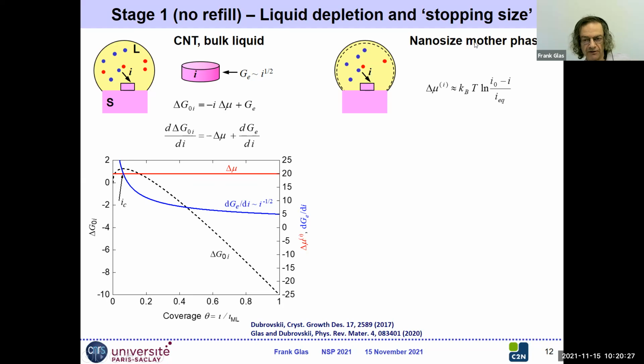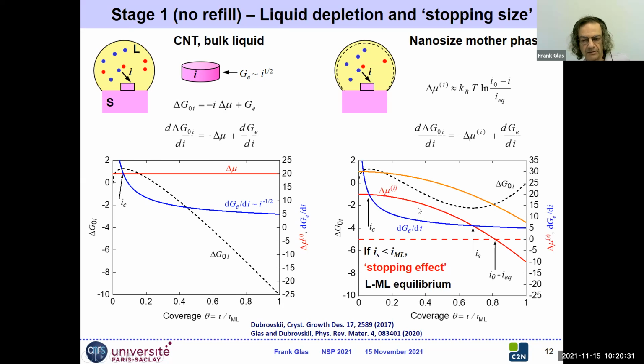So what about if we have a nano-sized monolayer phase as a nanowire? Then we can still calculate this derivative. And I'm not going into details, but the fact that we have the depletion of the liquid in arsenic atoms that I've mentioned means that the chemical potential will not stay constant. As I increase coverage, in other words, as I remove atoms from the liquid to the solid without refilling, because we're in stage 1, which goes very fast, the chemical potential will decrease, and decrease logarithmically with the coverage. But here it's only schematic. So we still have normally a first intersection of the delta mu curve and the derivative of the edge energy, which for the moment I assume to be the same as in the bulk case. This is again our critical size. But because this decreases, and the log will decrease to minus infinity, there must be a second point where we'll have another intersection.